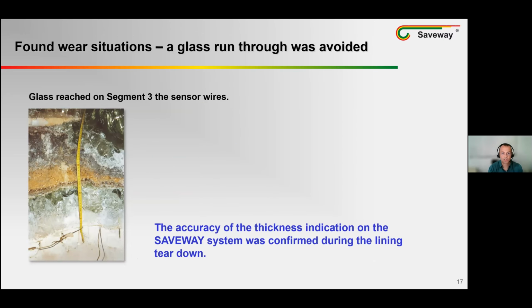In the picture you see now, segment 3 detects that the glass has reached the sensor electrode. System alarms were displayed. During the lining teardown, the accuracy of the system was confirmed according to the actual dimensions of each part. In the other segments, different conditions of penetrations were detected. In this way, a glass run-through will be avoided.